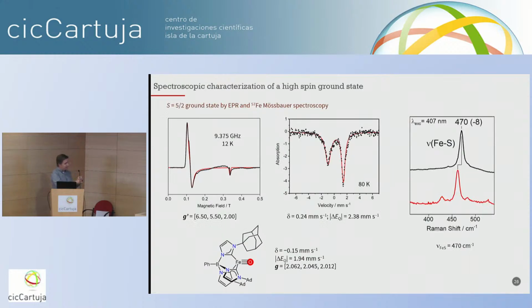And the reason for this difference in bond lengths is actually that the spin state here is different. So this is actually spin 5/2. This is high spin iron(III), as best shown by the EPR spectrum, where the g tensors are consistent with 5/2.